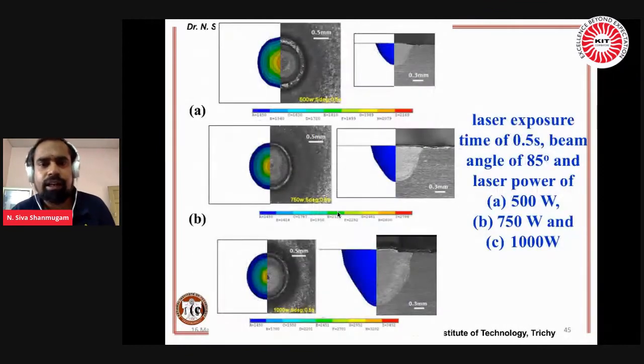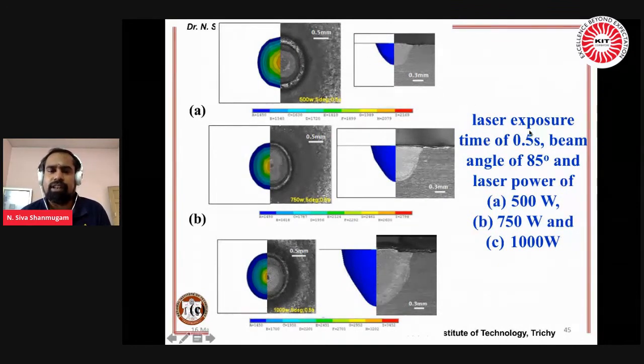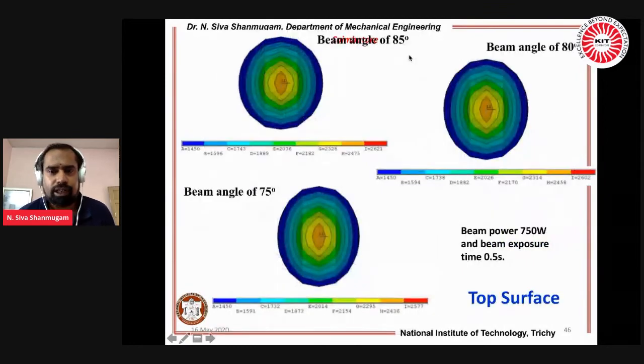Clear? And for different exposure times, with different bead geometry, with different process parameters, I have compared my finite element simulated results with the experimental results on both the top surface and along the thickness direction. See, these are all different surfaces. You can see the parameter effect. When you go with the wider beam angle, you are getting almost elliptical. This is almost a circle.